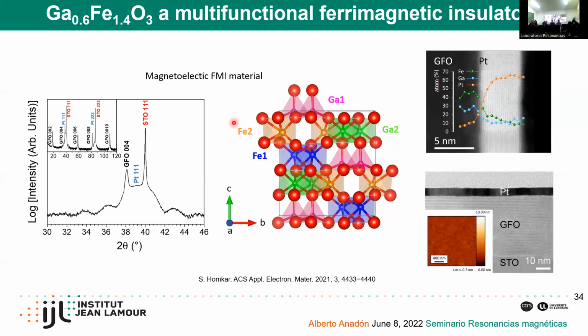So what we are doing this in collaboration with our colleagues in Strasbourg. They are able to produce these samples by pulsed laser deposition. As you can see, also, I'm very lucky with all my collaborators because they are also able to grow very good samples. And as before, they are very good in terms of crystalline coherence and clean interfaces and crystalline systems.